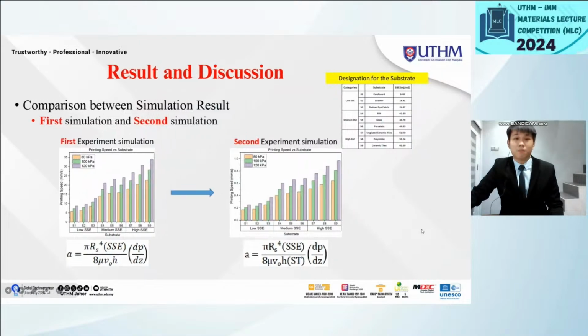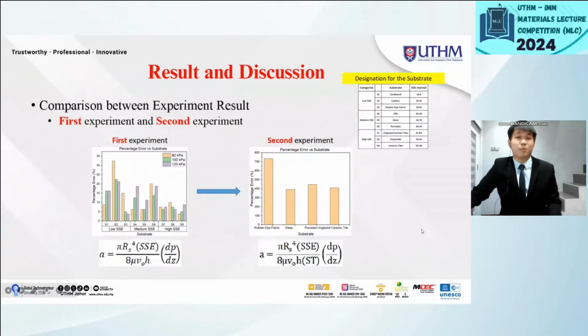For the comparison between the first experiment and the second experiment, the graph shows that the percentage error increased after integrating both substrate surface energy and ink surface tensions into the existing models. In the second experiment, the highest percentage error is 733.75%, while the lowest is 381.25%. This significant increase in percentage error is even worse than the existing models without additional variables. This is attributed to the increase in line width resulting from the decreased printing speeds.